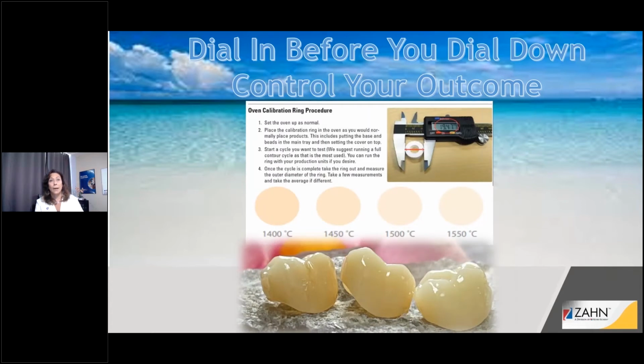All right, so how do you calibrate and make sure that you're going to get accurate results? I'm not going to dive too deep into this because my friend Daniel Alter has thoroughly gone over this topic, and I believe there is a webinar through Zahn if you really want to get deep into the calibration process. But basically, you can get a calibration ring from Zahn. You would put it in the furnace, sinter it on the appropriate program, and when the ring comes out, you would measure it. Based on that measurement, there would be a conversion chart, and it would tell you what the actual temperature in your furnace was.